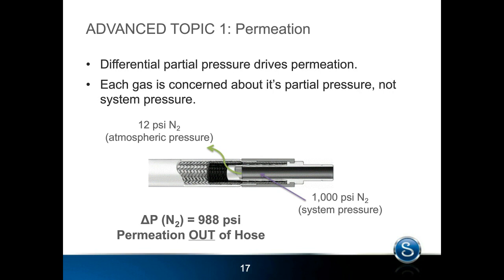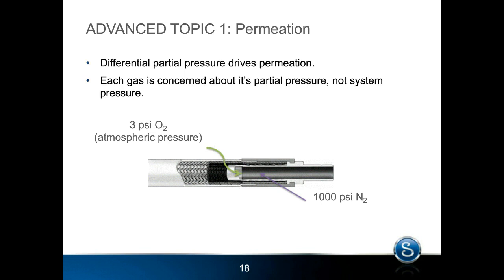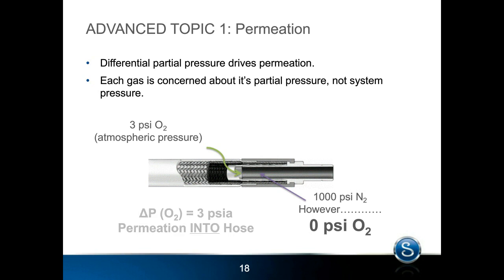What people don't always understand is that there's 0 psi oxygen on the inside of this hose, and there's 3 psi oxygen on the outside. People tend to assume that 1,000 psi of nitrogen will stop the oxygen from permeating in, and that's absolutely incorrect. Oxygen will permeate into this hose at a slow rate because it's only 3 psi, but it will permeate into this hose. So that's something that not everyone really is aware of, and it can affect the way hoses work if it's important to keep oxygen out of a system. In this case, it will not. It will permeate into the hose. So it's important to understand the partial pressures of every gas that's surrounding a hose if permeation is a concern.